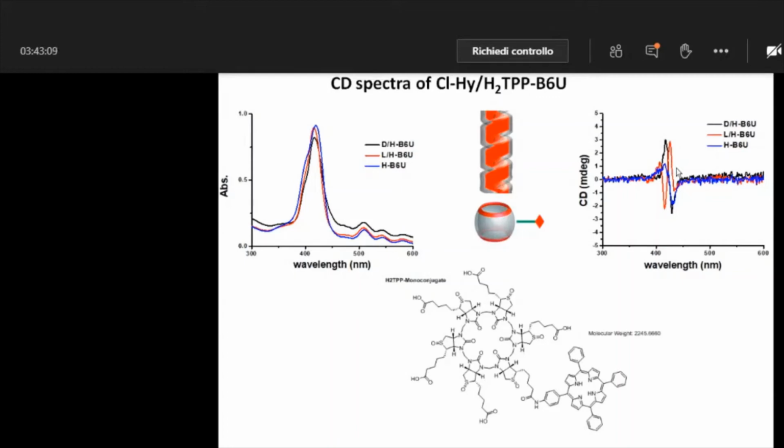If you don't have this opposite-handed CD, and it's the same as the monoconjugate, then it would suggest that the CD features coming in this region, without the opposite handedness, are mainly because of the intrinsic CD features of the monoconjugate and not because of chiral induction from the helices to the monoconjugate.